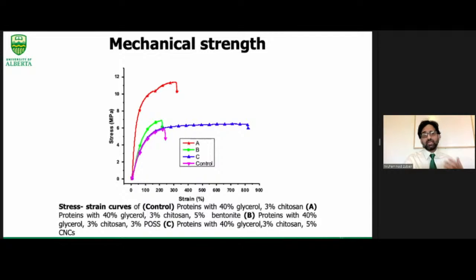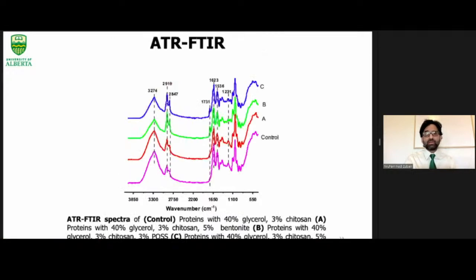A is basically the maximum tensile strength with the addition of bentonite, that we obtained around 12 megapascal. And we can see from the control how much increment has been obtained for mechanical strength by the addition of the nanoparticles. Furthermore, these films were characterized using FTIR. FTIR was used basically to see the structural changes after the addition of the nanoparticles into the protein's matrix.